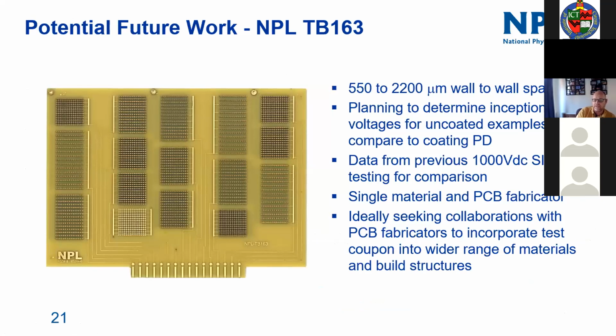The other thing we potentially would like to do is look at via breakdown. We've done this with 1,000 volts DC previously, and we've seen significant differences between the breakdown at these higher voltages and what might be expected if you extrapolate from lower voltages. At the moment, we're planning to look at this simple PCB that ranges in wall-to-wall spacings from about 0.5 millimeter up to just over 2 millimeters. We'll do some inception voltages on uncoated samples of this, just to see what the inception voltage is within PCBs, but it will only be a single material on a single PCB fabricator.